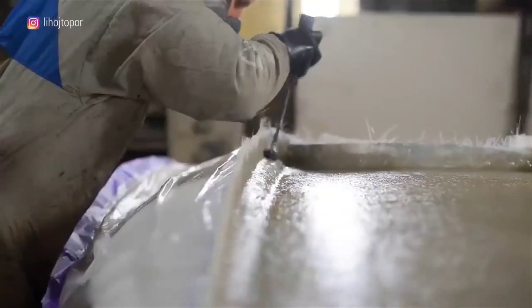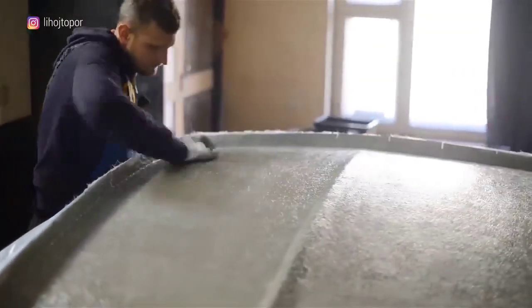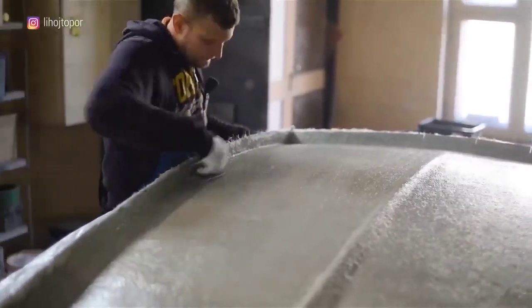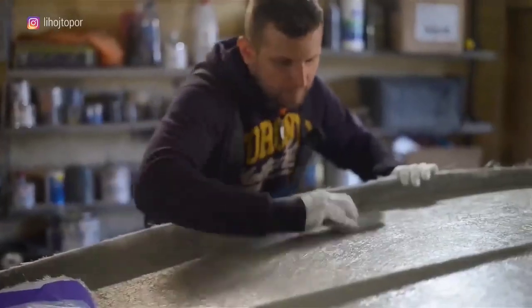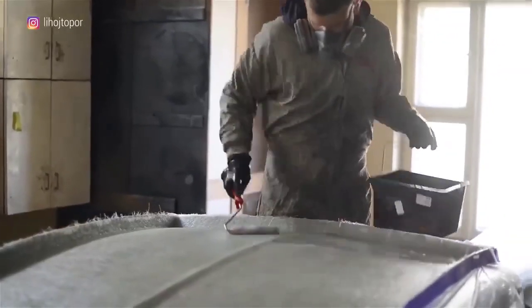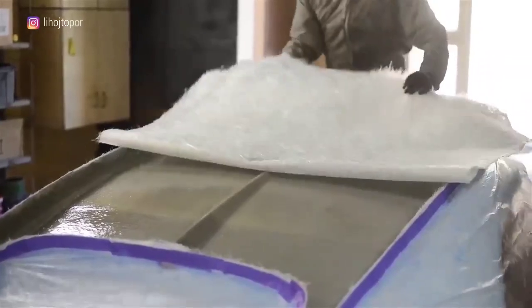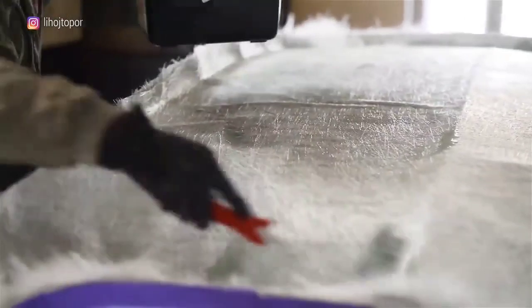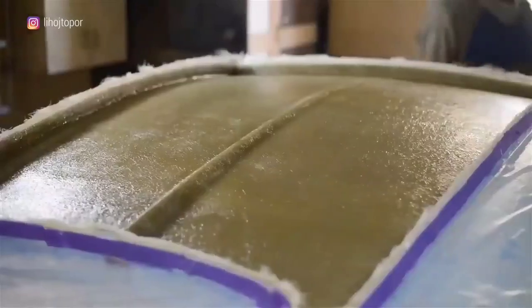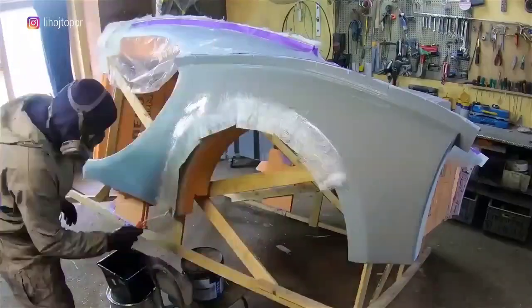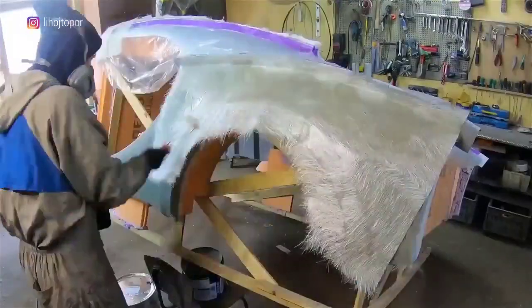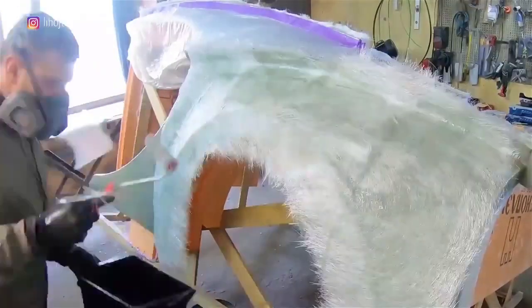In the end we used this metal roller with needles to remove all the air that remains under the glass fiber mat. Before applying the next layer we run a coarse sandpaper over the entire area to remove the obvious roughness and needles from the glass fiber mat. In the end, in order to create a more or less rigid matrix form, we put 2 layers of 300 mat, 3 layers of 450 mat and 2 layers of 600 mat. It took 132 pounds of polyester resin, 9 pounds of gel coat and a lot of workdays for Andre.